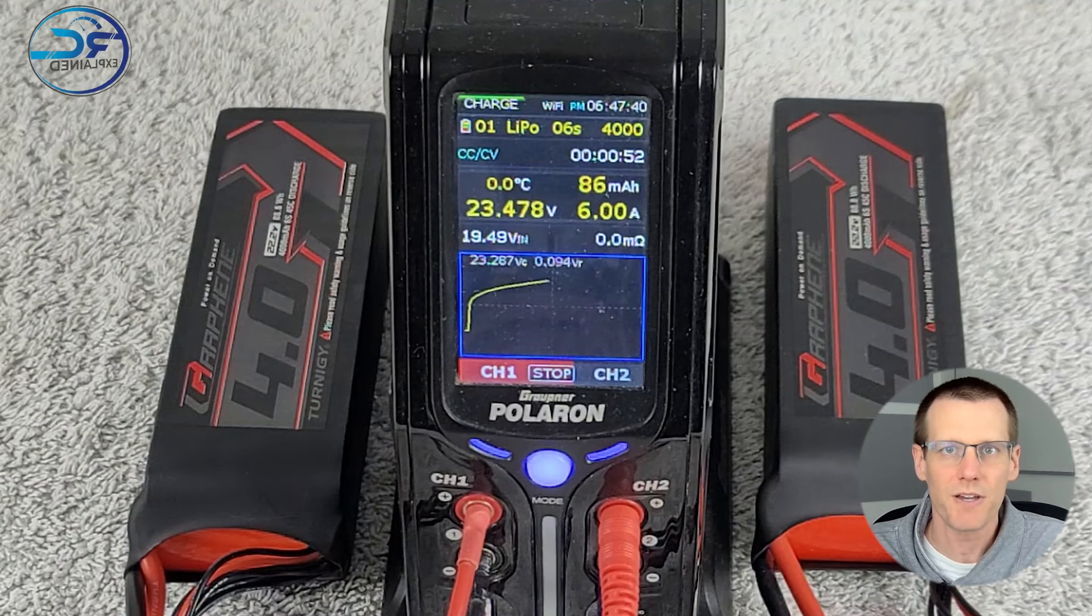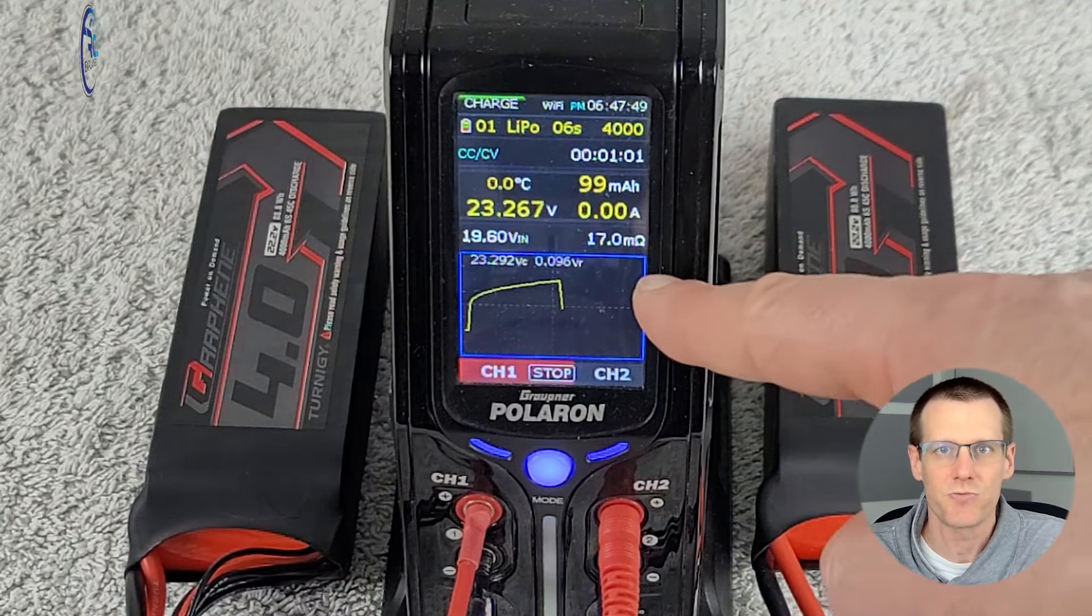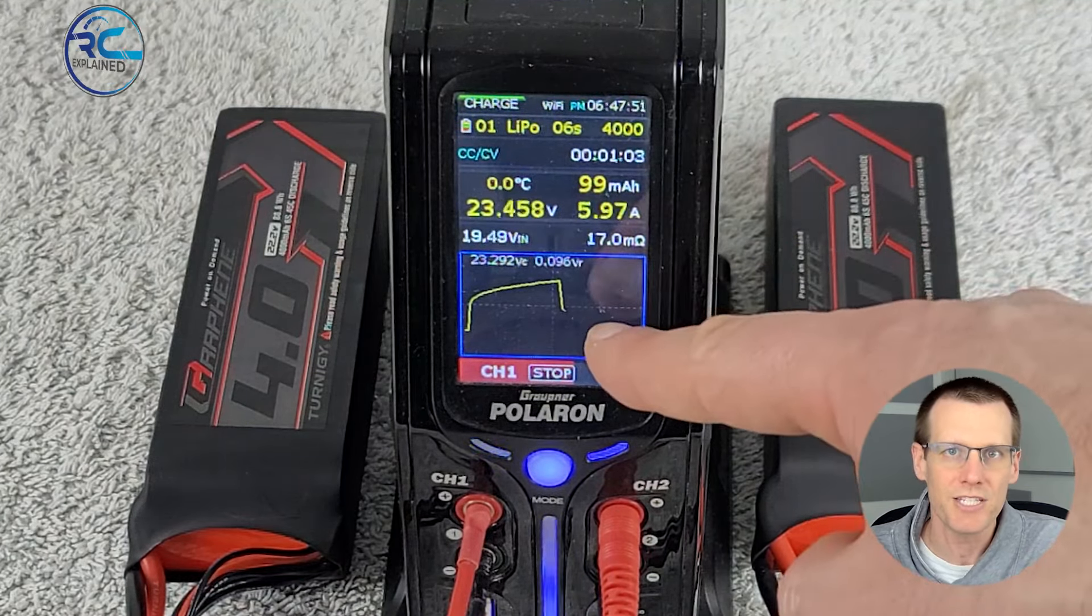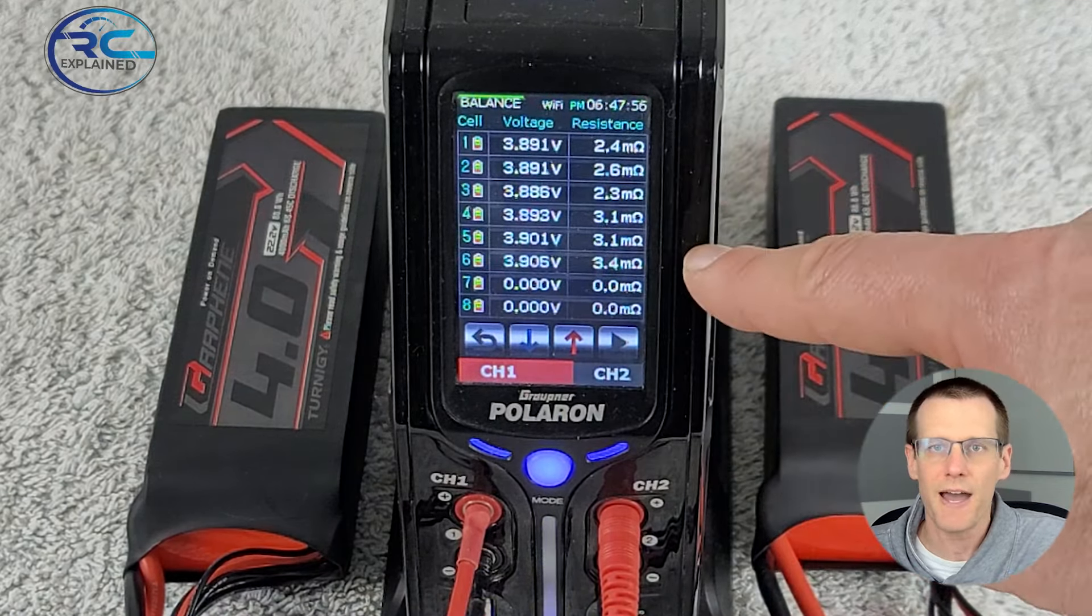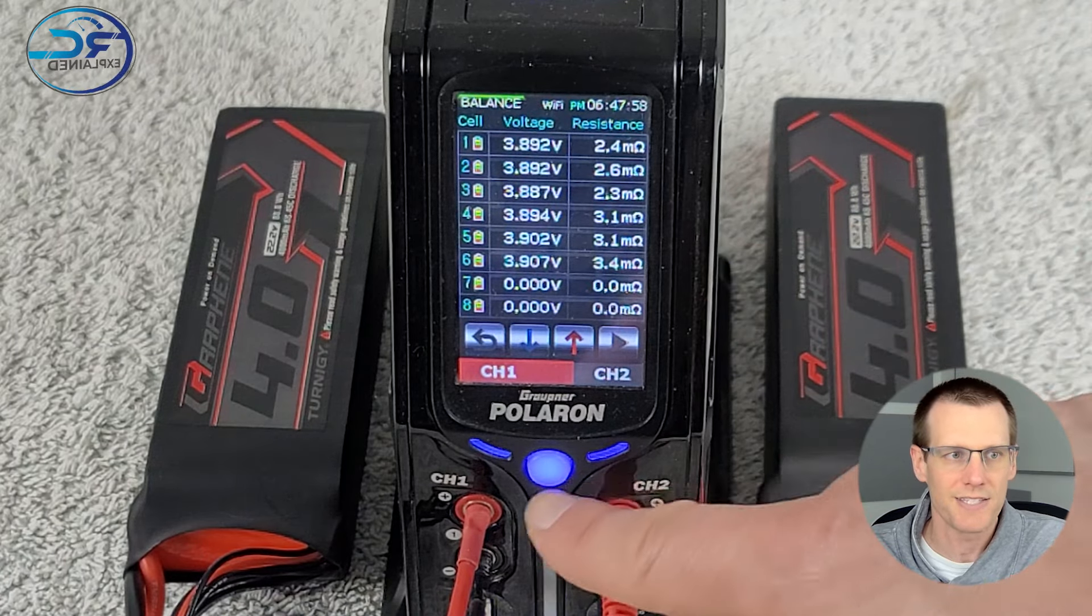And now we're accelerating the time to get to the one minute mark. At one minute, this specific charger takes the internal resistance readings. And that's the time I would suggest for you to take these readings as well, when you're charging for only one minute. If you go beyond that, you get values that are not as consistent.